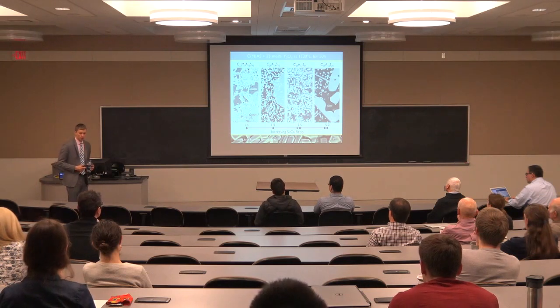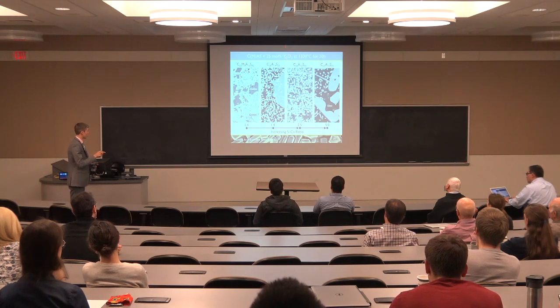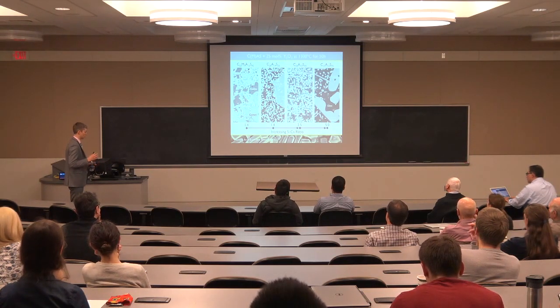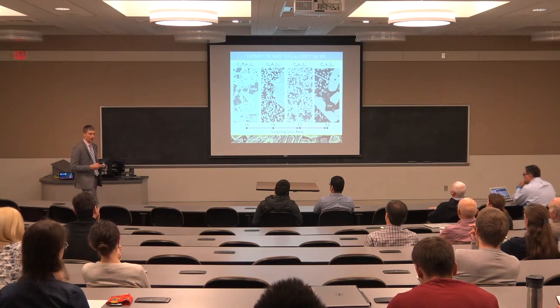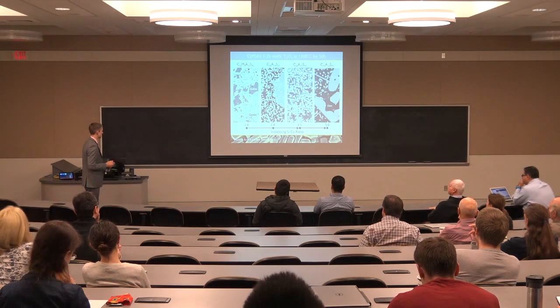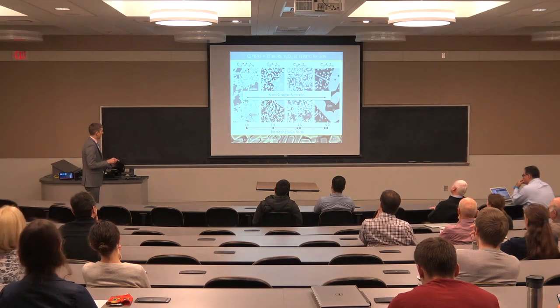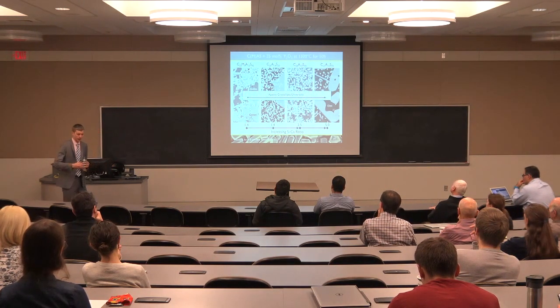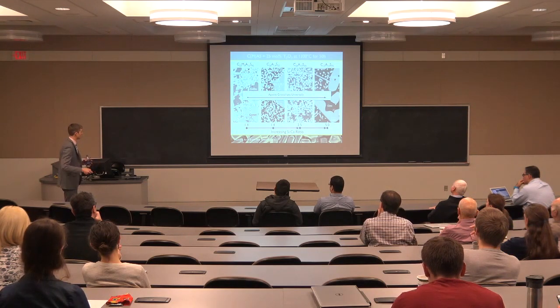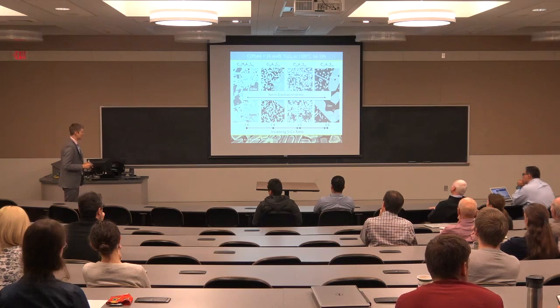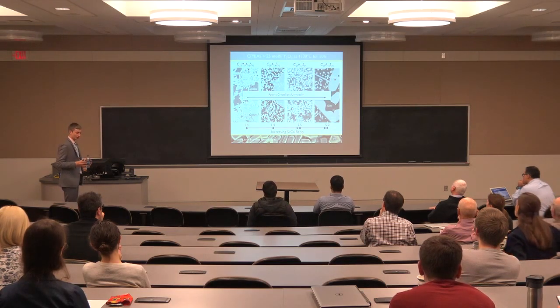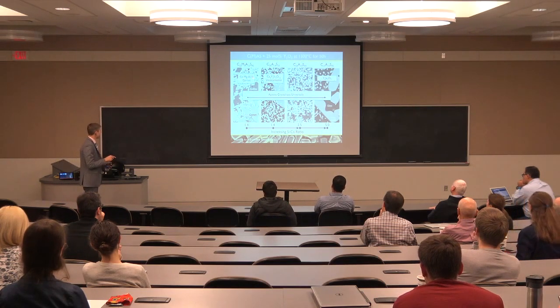We can then look at the equilibria with yttria, since this is one of the oxides that makes up a lot of the coating materials that are of interest. One of the things we find is that over this entire range of deposit compositions, with large changes in the calcium-silica ratio, apatites crystallize pretty universally. And as I've said, in some cases that's good, and in some cases it's not so great.